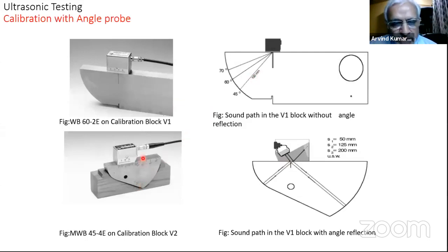Here you have a V2 block, a smaller block which can be carried to the field, which has dual curvature. It has a curvature here and a curvature here. This curvature is 25 mm and this curvature is 50 mm. If I keep my probe facing this curvature, then my first echo will come from 50, and the second echo will travel 75, but it will not get picked up because the probe is facing in the other direction.